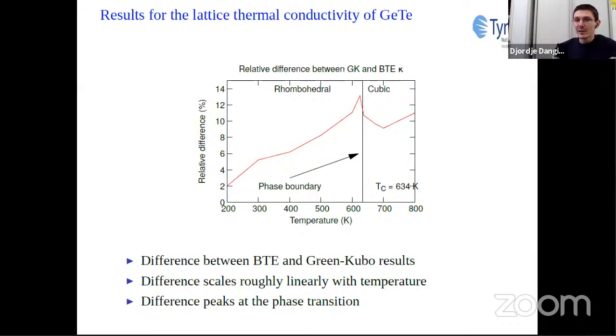First, I'm showing the relative difference between results obtained with the Green-Kubo method and results obtained with the Boltzmann transport equation. We notice that the Boltzmann transport equation consistently underestimates the results from the Green-Kubo method. We can also notice that this underestimation is not large. At most, it's around 14%.